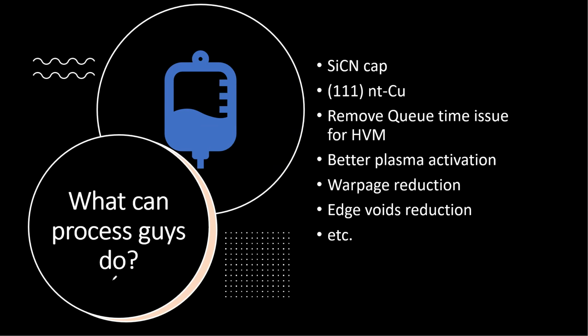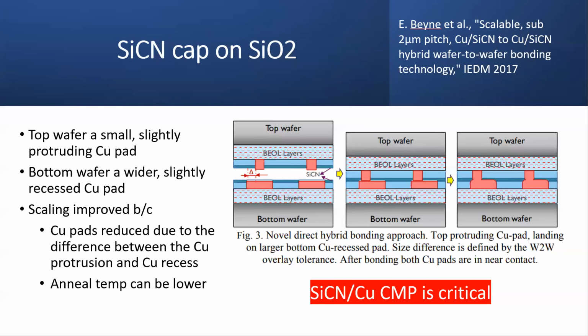And from the process guy's side, well, I can't change the tool, but what I can do is change some material and some process on the material. So that's what I can summarize for you here. First, silicon carbon nitride cap, and then the 111 nano twin copper. Better plasma activation, and warpage reduction, edge voids reduction. Currently many experts provide their expertise to try to improve the overall scaling and the overall HBI process technology.